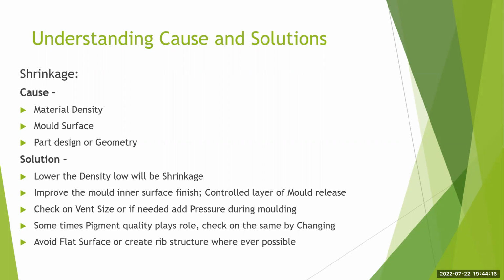It's very important. Sometimes we extensively use mold release. Now, you think mold release is beneficial, but it is not always. If you put mold release on improperly, the layer is not cleaned properly, or it has been applied unevenly, then rather than finding a solution for releasing the product, you start creating problems. Mold sticking will take place, the shrinkage will be uneven, and product warpage will be seen. So whenever you use mold release, use standard mold release chemicals, and clean the surface area before you go into production. It is very, very important.